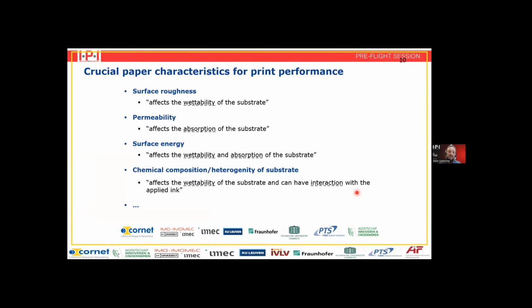If you look at the properties of the paper or the fiber-based substrates only, you of course have the surface roughness, which affects the wettability of the substrate. Also, the permeability was very important. That links to the absorption of the ink onto or into the substrate. The surface energy is something that we measured, affecting the wettability and the absorption of the substrate. And then, of course, the heterogeneity of the substrate or the chemical composition, and many more of these characteristics were